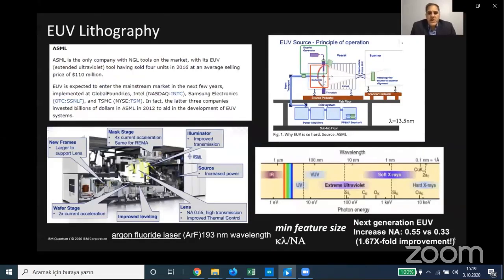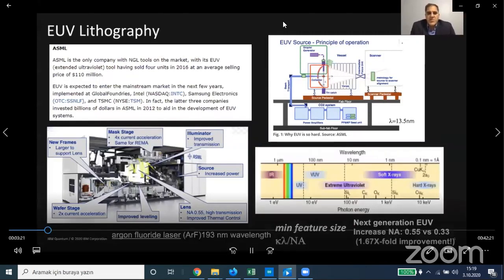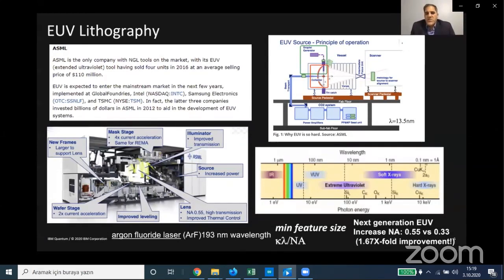I briefly described capital costs. So one very expensive tool is the EUV, or extreme UV lithography tool, which is used to write critical features. Shown here is the minimum feature size. The equation goes as k lambda over NA, so it goes linearly with the wavelength. Most features in nanoscale transistors, for the most part, are defined by argon fluoride lithography, with a 193 nanometer wavelength. So you can see the EUV is more than a 10x reduction in the wavelength. So it really is a revolutionary step to scale the minimum feature size.